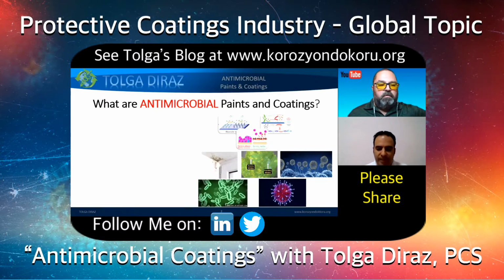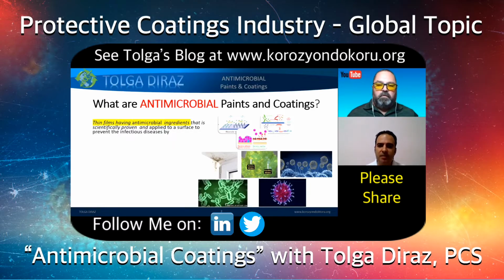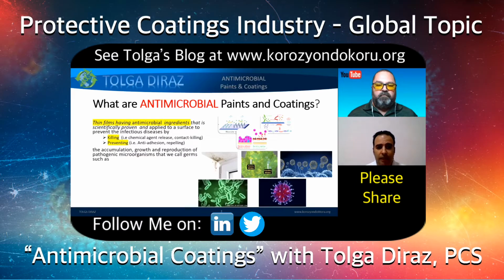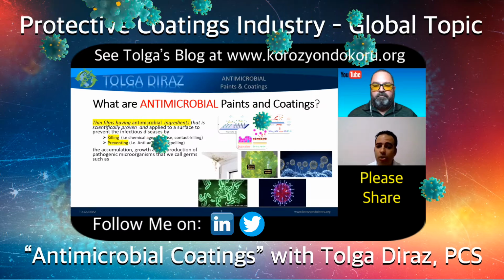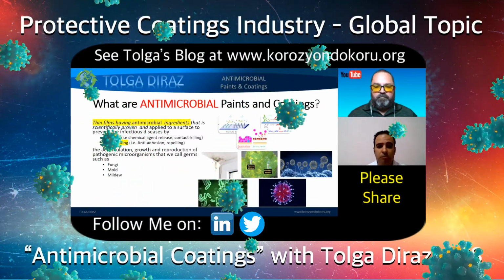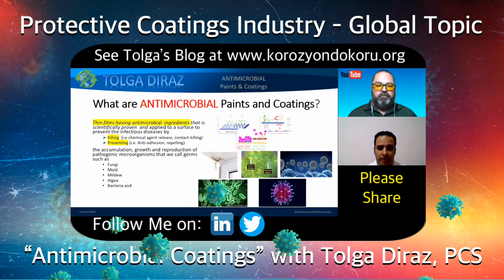James, as a globally accepted description, antimicrobial paints and coatings are thin films having scientifically proven antimicrobial ingredients, applied to a surface to prevent infectious diseases, first by killing mechanisms, like chemical agent release and contact killing, and secondly by preventing, like anti-adhesion and repelling. We are killing or preventing the accumulation, growth, and reproduction of pathogenic microorganisms that we call germs, such as fungi, mold, mildew, algae, bacteria, and viruses.